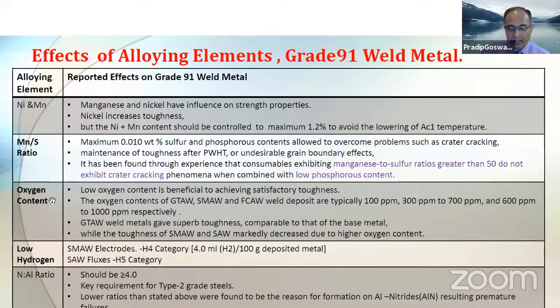Oxygen content. This is a critical aspect of this alloy. Generally, lower oxygen is beneficial for good or satisfactory toughness. With respect to the oxygen content of TIG, shielded metal arc and flux core arc welding, the content may vary typically from 100 ppm for TIG, 300 to 700 for SMAW, and typically 600 to 1000 ppm for flux core arc welding.